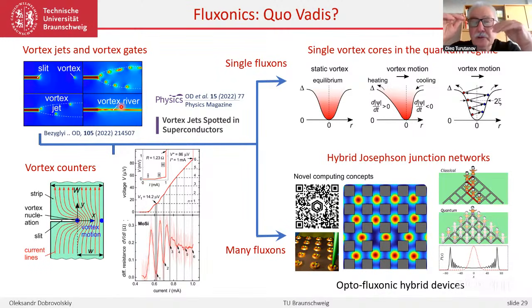Yeah, the cores are overlapping. And also there is a topological transition for the screening current. So there is a global screening current, like in a wide Josephson junction. And also for microwave characteristics, there is a jump in frequency because you don't have this factor n corresponding to the number of vortices, but now you have a Josephson frequency. Maybe in other words, this is the same as a phase-slip line. Yes, it is a phase-slip. Exactly, it is a phase-slip line, just other words.